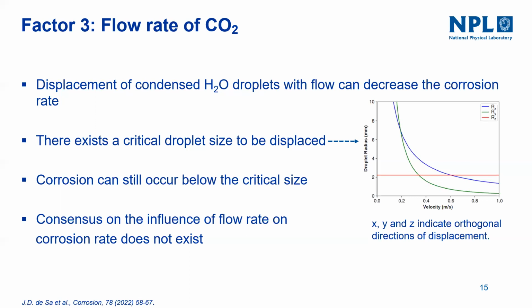In the majority of the studies, what has been observed is that flow rate increased the corrosion rate significantly, by one order of magnitude, while different groups have indicated a negligible difference, and other groups have indicated no difference. So right now, the current status is that there is no consensus on the influence of flow rate on corrosion rates.